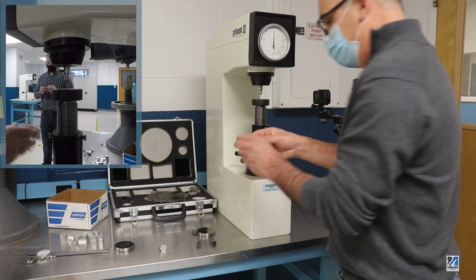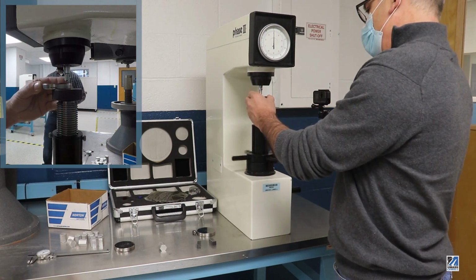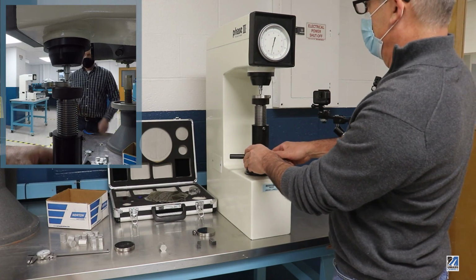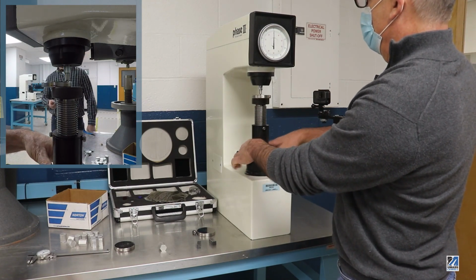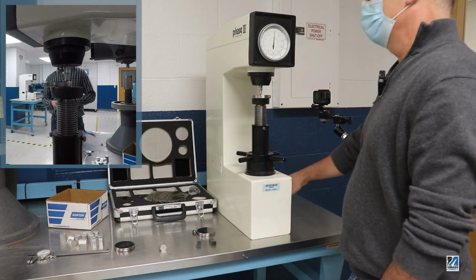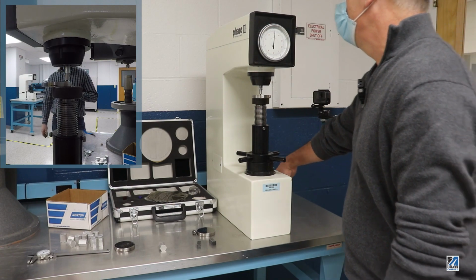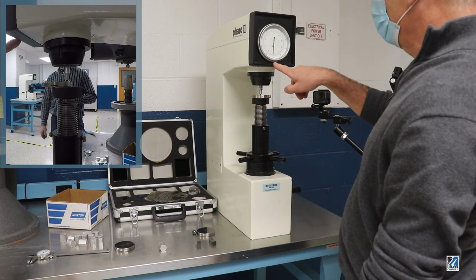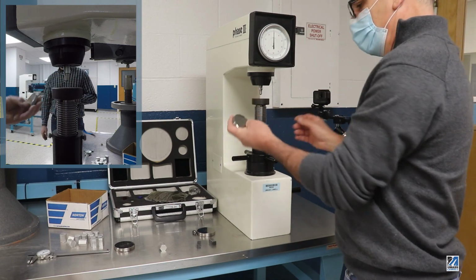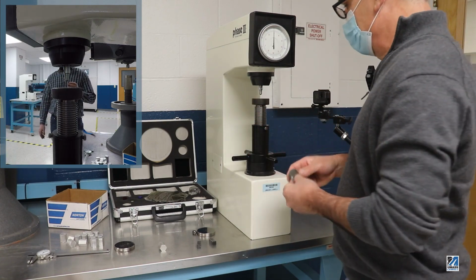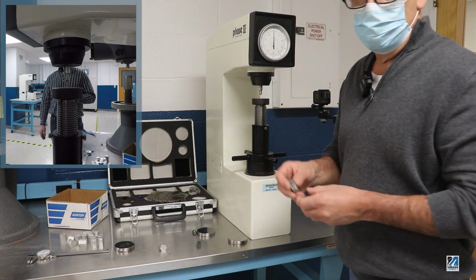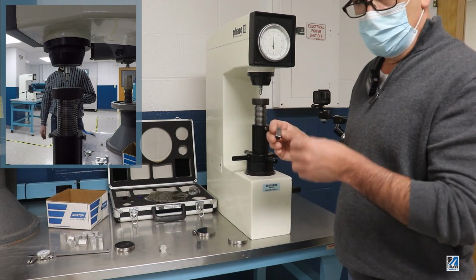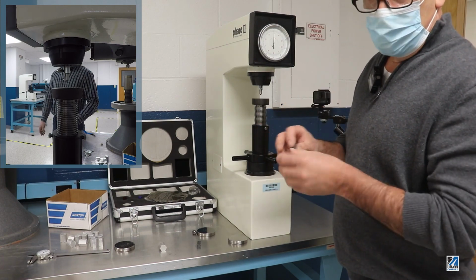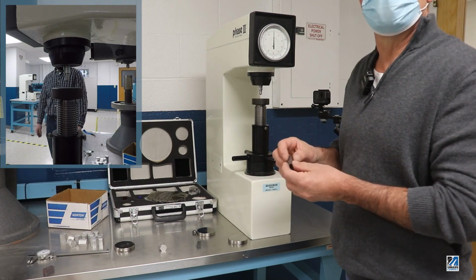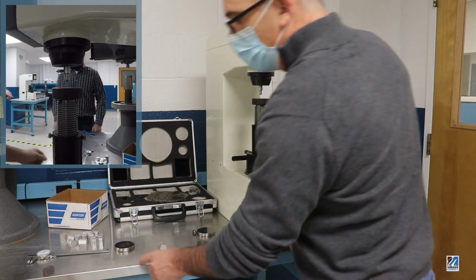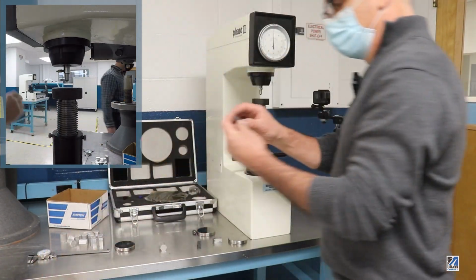But again, I'm going to quickly check the machine with a standard. Oops. Apply the major load. And I'm at a Rockwell of approximately 50 on a C scale. Again, I'm off by a couple points on a Rockwell Hardness C. So that tells me that the machine is on, and I would have deviations in the hardness along maybe the length or on different sides, depending upon how it was actually heat treated and quenched. That concludes that portion.